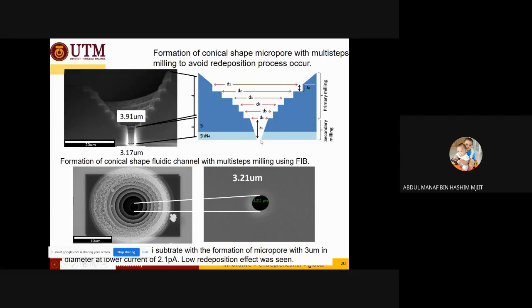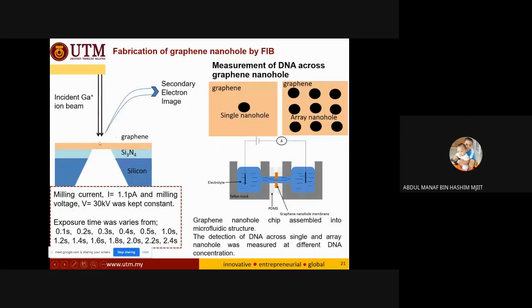So this is a schematic here, and the idea is that after that we put a graphene on top of the conical shaped micropore. Later on we proceed with another FIB step to make a nanohole here. Then with this structure, we proceed with the DNA measurement.